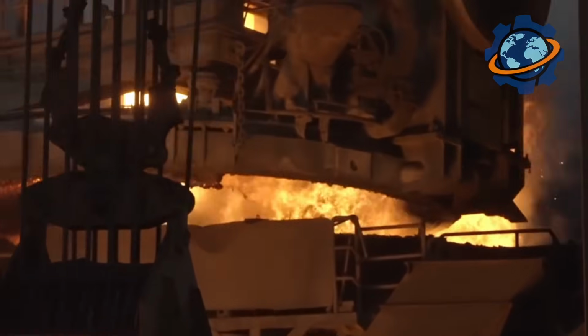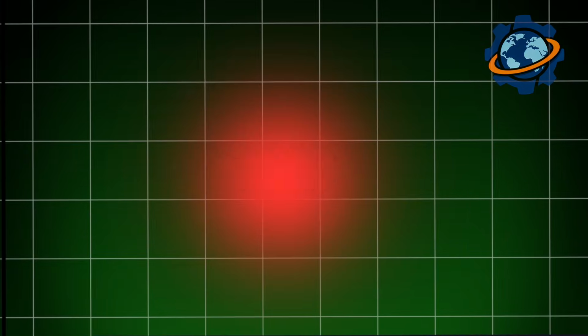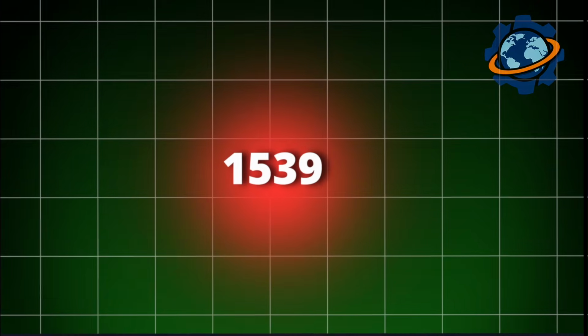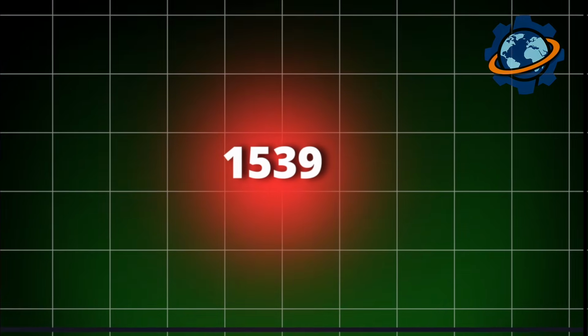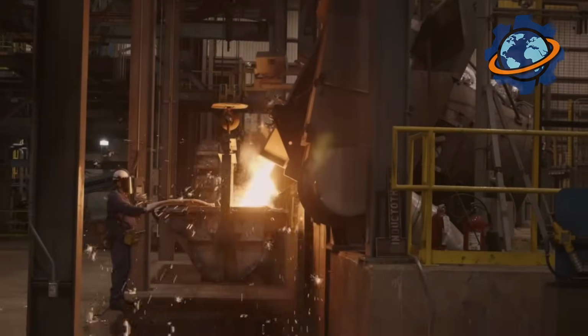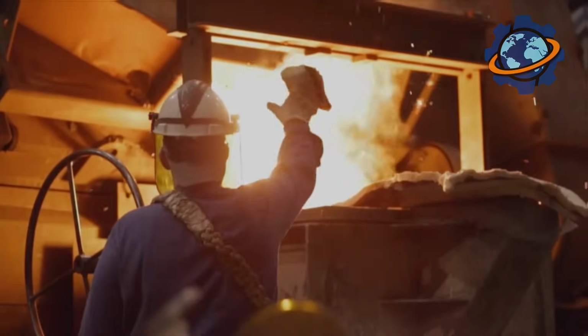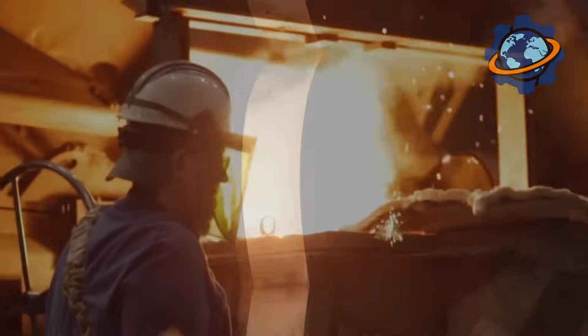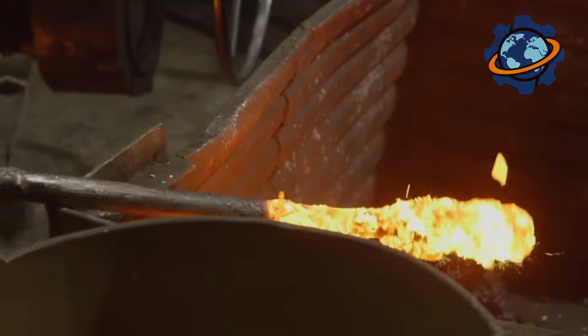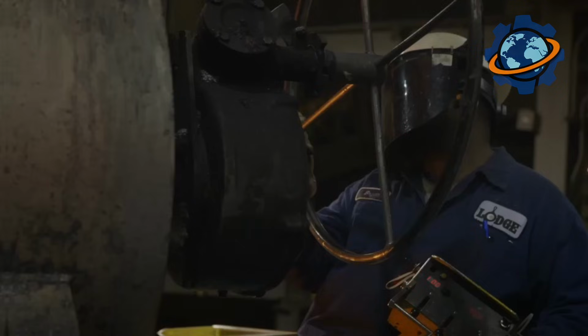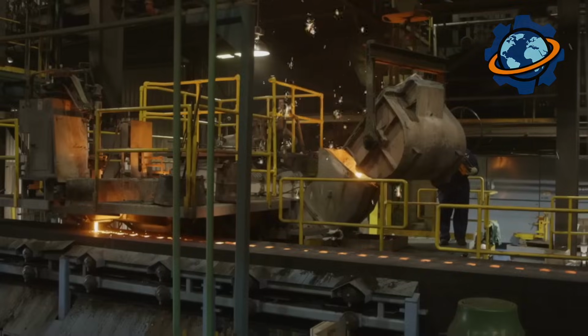Pure iron melts at a very high temperature of 2,800 degrees Fahrenheit, 1,539 Celsius. But soaking up carbon dramatically lowers that melting point. That's why a blast furnace doesn't produce pure iron, but an alloy of iron and carbon, pig iron, which becomes liquid at just 2,200 degrees Fahrenheit, 1,200 Celsius. Roughly every 40 to 60 minutes, enough liquid products have collected in the bottom of the furnace.